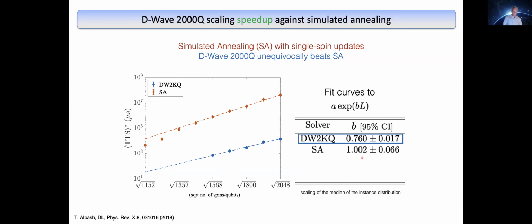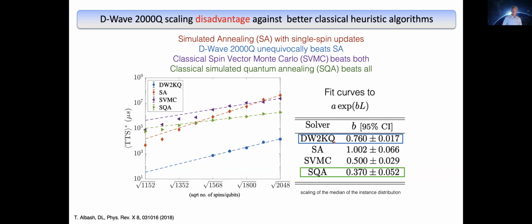However, unfortunately, simulated annealing is not the best algorithm in this situation. And when we benchmarked the very same problems using SVMC, the spin vector Monte Carlo, and simulated quantum annealing, SQA, we found that both, but especially SQA, was doing very well and had a better scaling. So once more, no scaling advantage result except against simulated annealing. Okay, so still no luck really.